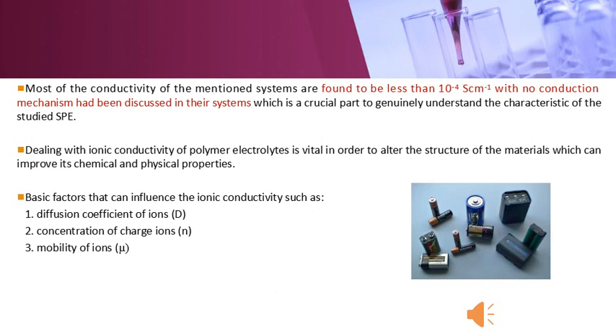So dealing with the ionic conductivity of polymer electrolytes is vital in order to alter the structure of the materials themselves, which can improve their chemical and physical properties. The basic factors that can influence the ionic conductivity of SPE films are the diffusion coefficient of ions, the concentration of charge ions, and also the mobility of ions. Besides, the common ways to estimate these transport properties are using electrical impedance spectroscopy (EIS), the Bandara and Mellander approach, and also the FTIR technique.